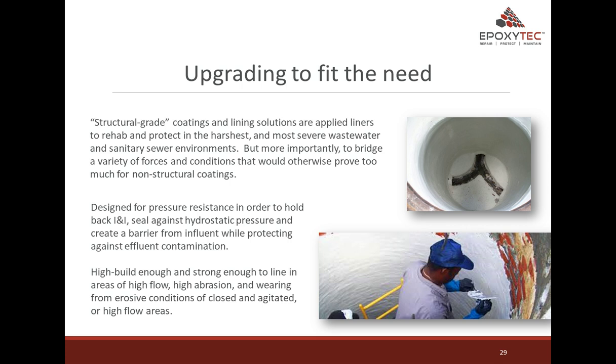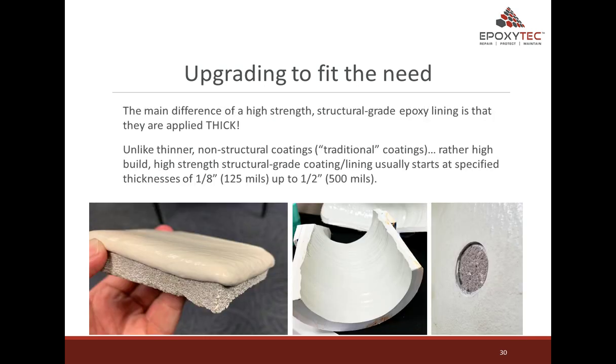Structural grade coatings and lining solutions are applied liners to rehab and protect in the harshest and most severe wastewater and sanitary sewer environments, but more importantly, to bridge a variety of forces and conditions that would otherwise prove too much for a non-structural coating. Designed for pressure resistance in order to hold back I&I, seal against hydrostatic pressure, and create a barrier from influent while protecting against effluent contamination. High build enough and strong enough to line in areas of high flow, high abrasion, and wearing from erosive conditions of closed and agitated or high flow areas.